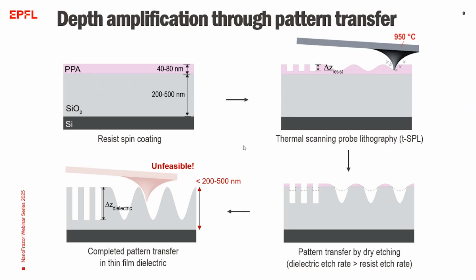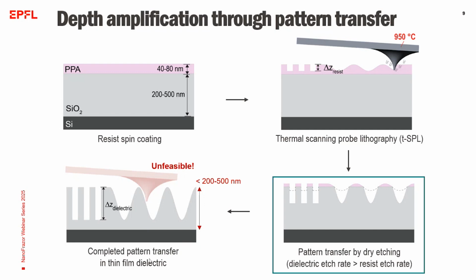However, with depth amplification through pattern transfer, as I mentioned earlier, we overcome this limitation and reach higher aspect ratio grayscale pattern that standard tip cannot achieve. As you can see here, we can reach much higher depths than the tip size. And now I will share some of the details about the plasma etching step, which is the third step in this process flow.